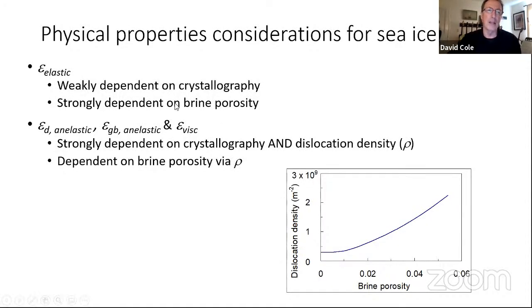Now, how do these relate to the physical properties? Well, elasticity is weakly dependent on the crystallography. It turns out that for sea ice, there's a very strong dependence that is in fact different between lab experiments and in situ experiments. We don't exactly know why, but I'll show you this fairly dramatic change in elastic behavior between the two cases. But all these other components are dislocation based and are therefore strongly dependent on the crystallography as it relates to the resolved shear stress on the basal planes, because that's where all the dislocation activity is, and on dislocation density. With brine porosity just as grown, we see this increase. We don't have a huge range here, but as the brine porosity increases in the as-grown material, the dislocation density increases, for reasons that we can quantify but don't completely understand.